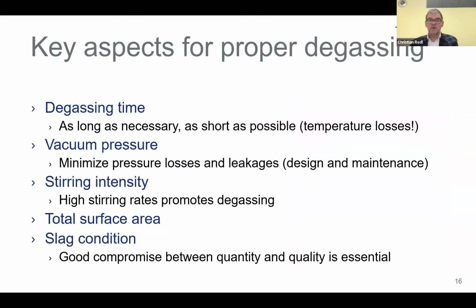Okay, the key aspect for proper degassing is, of course, the degassing time. It should be as long as necessary, but as short as possible to avoid temperature losses during the vacuum treatment. Of course, the longer the degassing time under deep vacuum, the lower will be the gas content of the melt. And the same is true for the vacuum pressure. The lower the vacuum pressure, the lower the final gas contents of the melt will be.